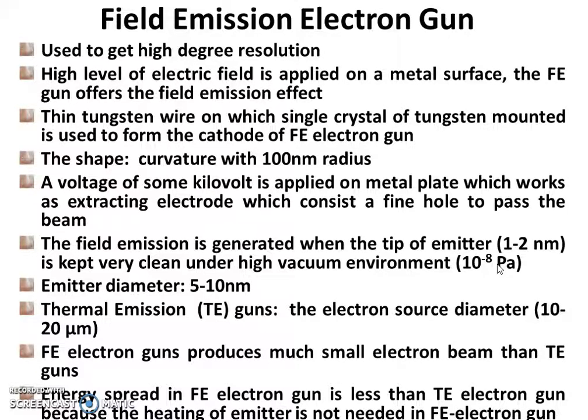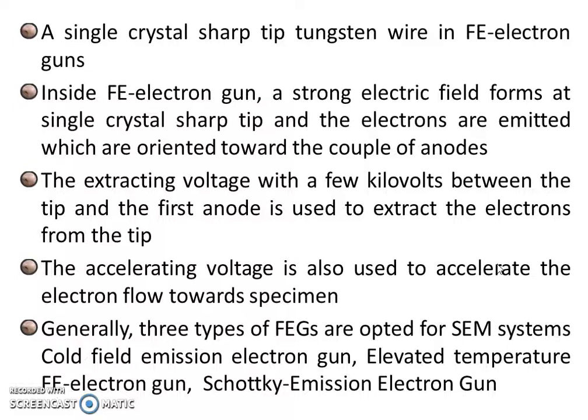FE electron guns produce a much smaller electron beam than TE guns, and the energy spread in an FE electron gun is less than in TE electron guns because heating of the emitter is not needed in FE electron guns. A single crystal sharp tip tungsten wire is used in FE electron guns. Inside FE electron guns, a strong electric field forms at the single crystal sharp tip, and the electrons are emitted, which are oriented towards a couple of anodes.